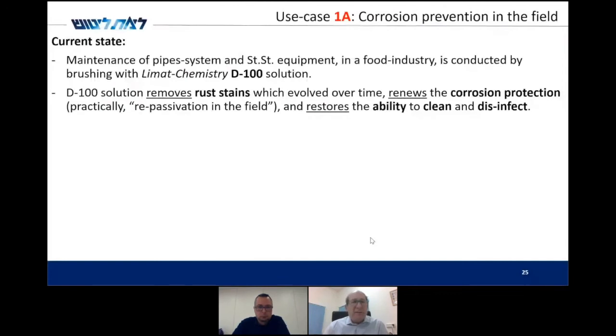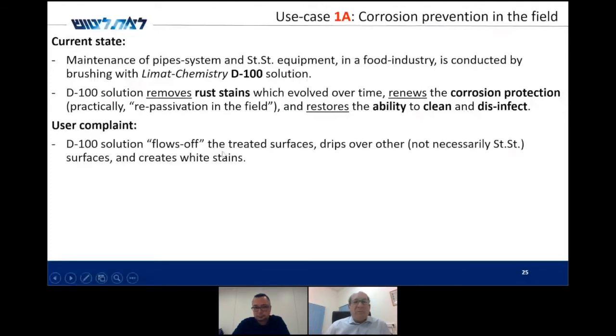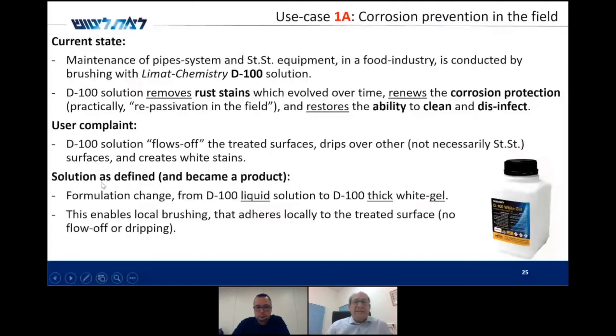And now I will very quickly touch some of the use cases that I meant, and please stop me whenever you think I'm over my time. So in one case, a customer was using our D100 solution to renew corrosion protection in the field, but he complained that it flows off the treated surfaces, drips, and creates white stains. And we were able to tailor to his needs another formulation for this field passivation liquid, making it a gel, which enables local brushing and adheres locally to the treated surface, so no flow-off or dripping.